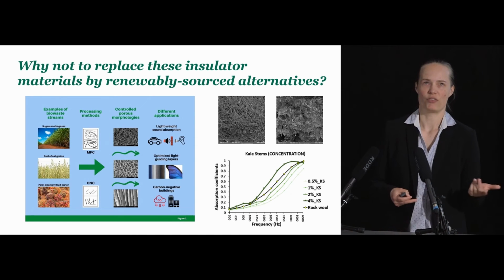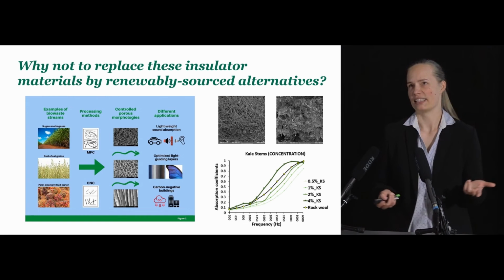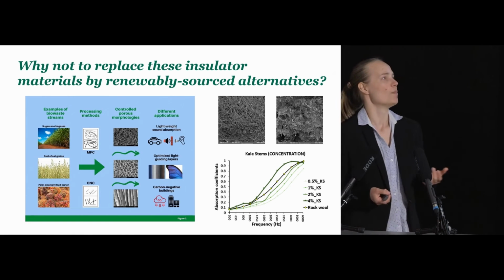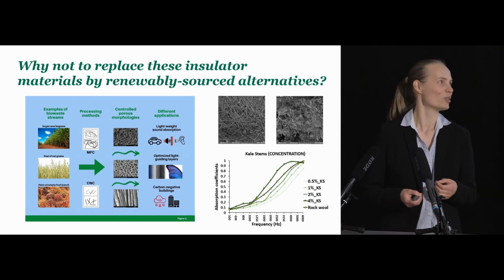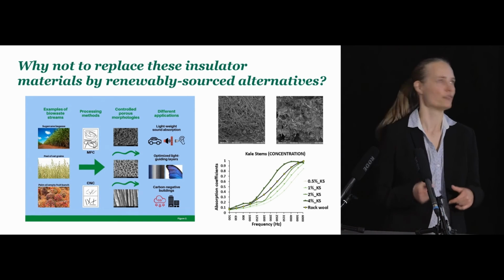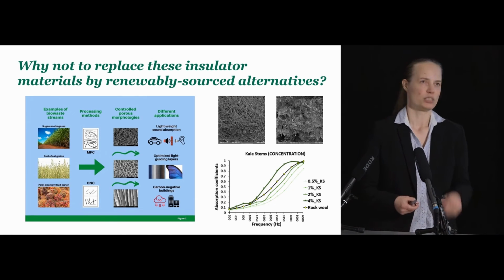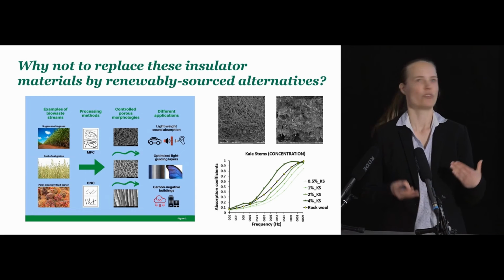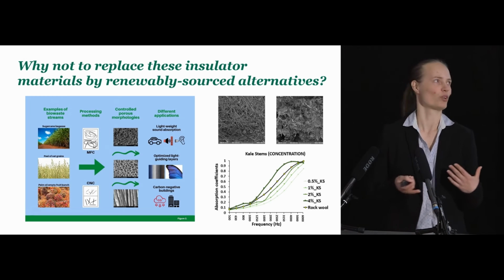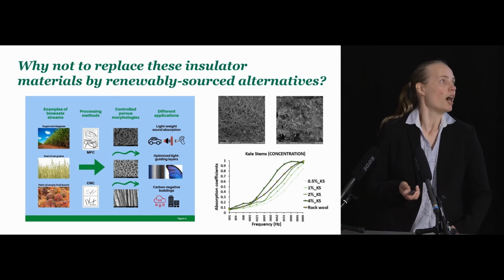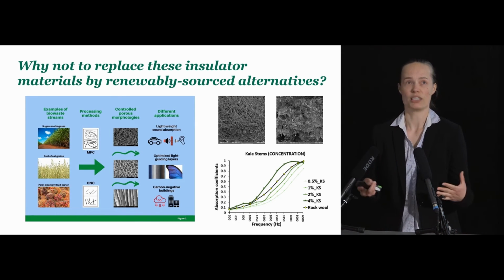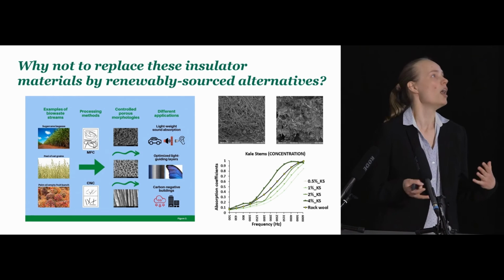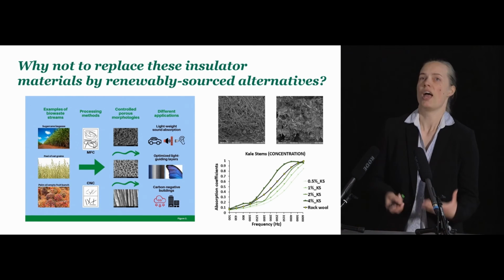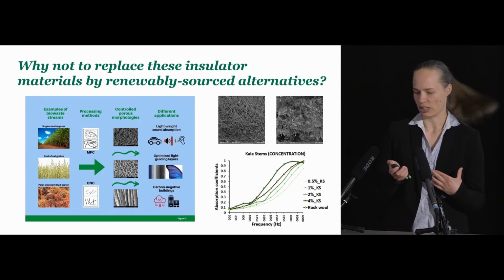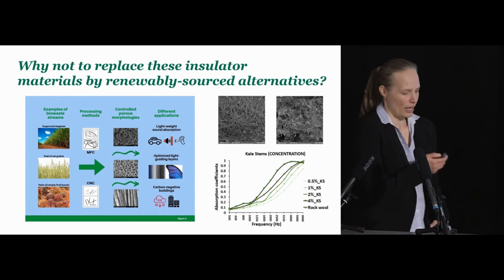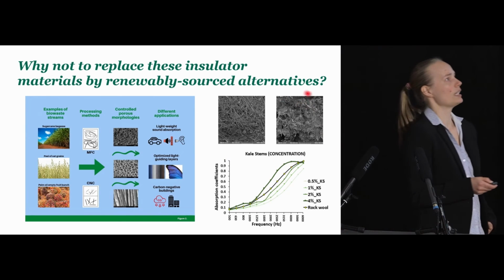And what we started from was this type of bio-waste sourced acoustic insulators. We tried three different types of bio-wastes, out of which kale stems turned out to be the best. What we actually did was that we took real kale from the garden, ate the leaves, and then ground the stem very small, and then applied this type of simplified CNC extraction protocol on this powder. We then got CNCs out of that, but because it was a very simplified process, also some lignin and some other residues were left in the suspension. We didn't let that disturb us, and we just freeze-dried those gels, and what we got was something that looked like this.